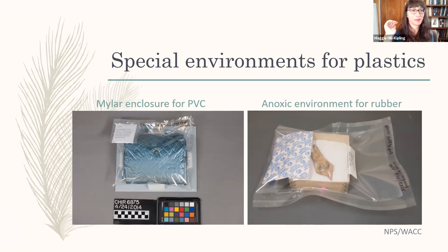So you're thinking of those, some of them are made to look like leather, a little bit rubbery surfaces, like this little pouch on the left. And one of the problems with PVC is that it seeps some of the plasticizers that are in the flexible PVC. PVC pipes don't have the same kind of issue as hard PVC, but the flexible PVC has plasticizers inside of it, which tend to seep out over time. And your normal plastics that you might be more familiar with using in storage, like polyethylene, actually can absorb those plasticizers and drive that reaction forward, where the plasticizers are leaching out, being basically sucked up by the polyethylene. And so we need to use very specific materials for storage of PVC to make sure that that doesn't continue.